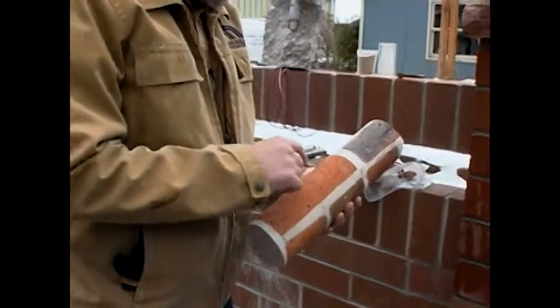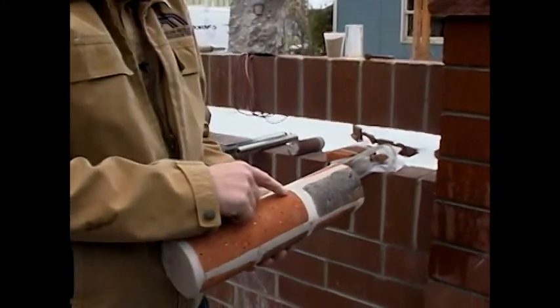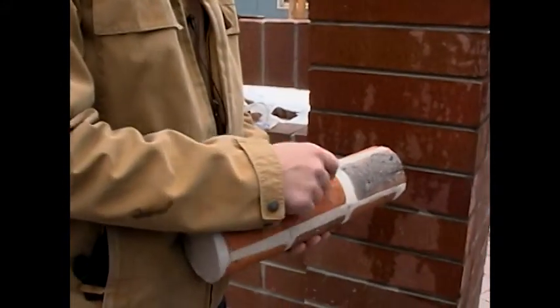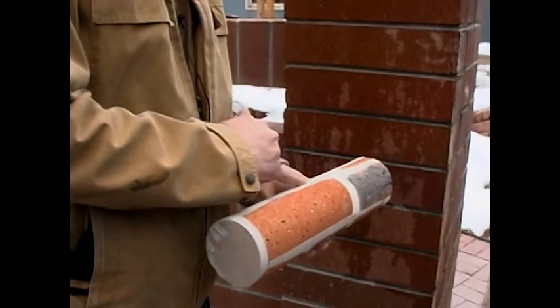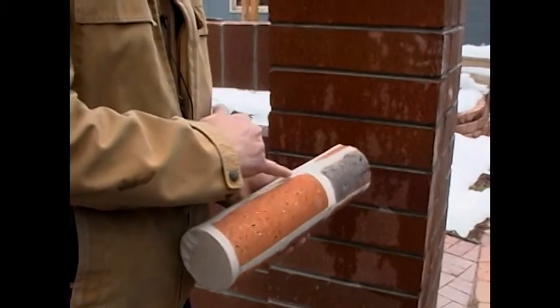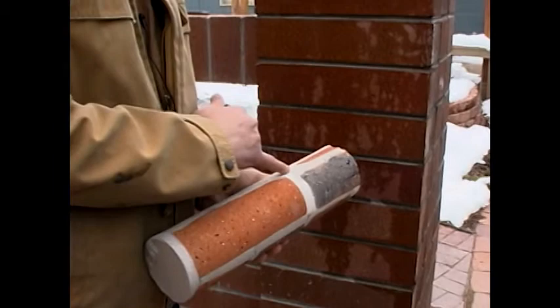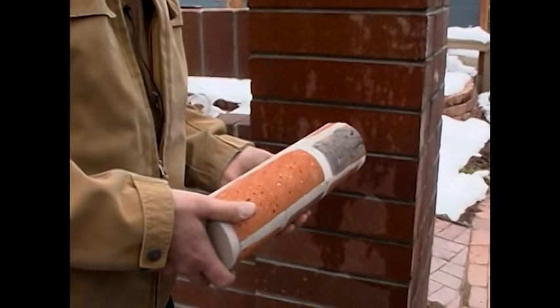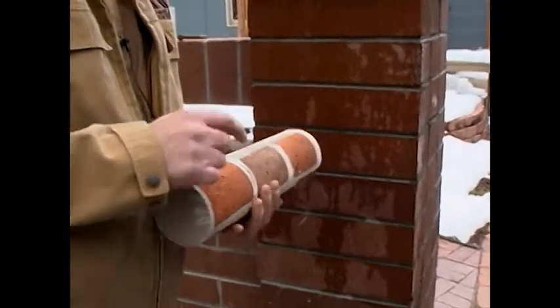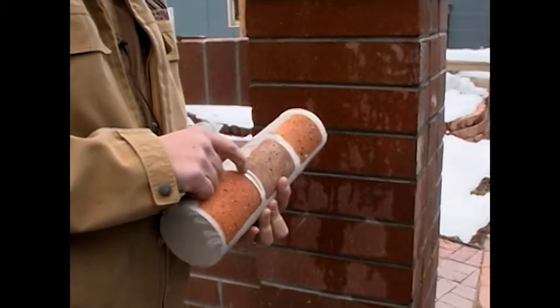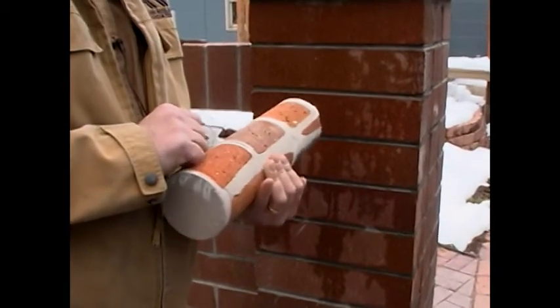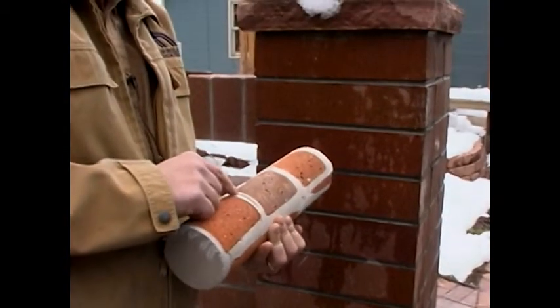And again, what we're looking at is really good contact between the injected material. In this case, it's the whiter material. You see the original mortar was kind of grayish. Really good flow into these little cracks and fissures. Good bond, no shrinkage. A little bit of settlement. That is not our best core, but it happens from time to time. You get a little air void in there.